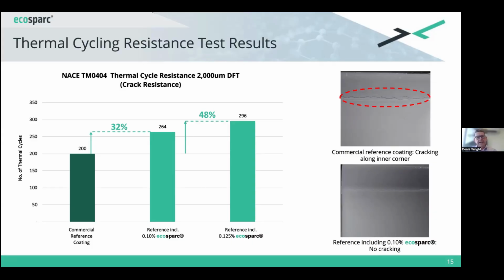We then had that coating and added more ecosparc to it, and that ecosparc addition caused an even further increase in the crack resistance in the number of cycles. So this coating has gone through 296 cycles before failure relative to the reference without graphene in it at 200 cycles. And so that's a significant increase. And whether it's 48 or 52 or 38%, it's still a significant increase. And that correlates out to a piece of steel on somebody's industry, or in the heat or in the sun, cooling down and heating up on an oil rig somewhere. It's going to improve how that steel behaves and how the coating on that steel behaves and mitigate corrosion.